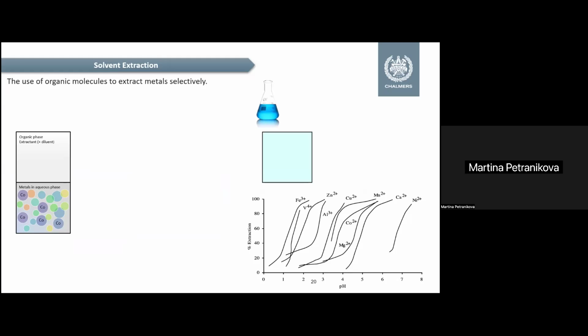Another method which has been used quite often for the separation of the transition metals is solvent extraction. Because transition metals are very similar to each other, it's not that easy to separate them just with the precipitation. So very often solvent extraction is used. It's a technique which is very old and being used in the primary production of metals. And the main principle is that we have organic molecules which are very selective. And very often we use molecules which we can trick by changing the pH. So if we set a proper pH of the solution and mix this solution with the organic phase, then we can get into this organic phase just the metal we want to recover.